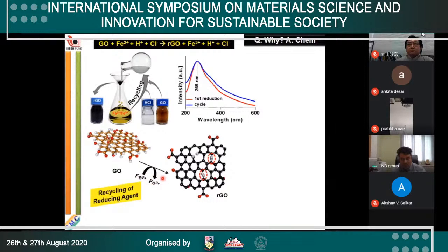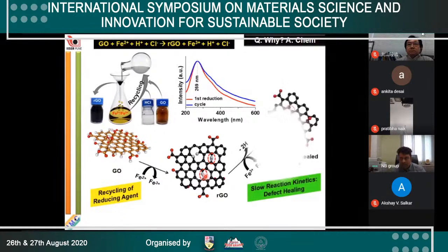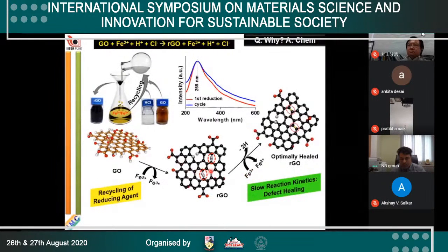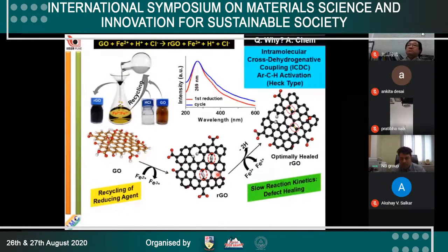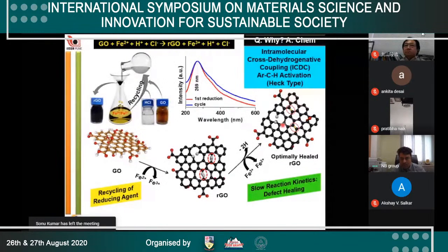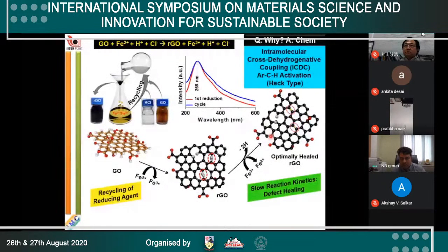Now iron 3 is a Lewis acid and these are aromatic CH. So in the next step, these aromatic CH are getting activated by this Lewis acid, so-called aromatic CH activation, Heck type of reaction, or intramolecular cross dehydrogenative coupling. As a result, these defects are getting healed. So this is an optimally healed RGO, and we are getting back iron 3 to iron 2 plus.